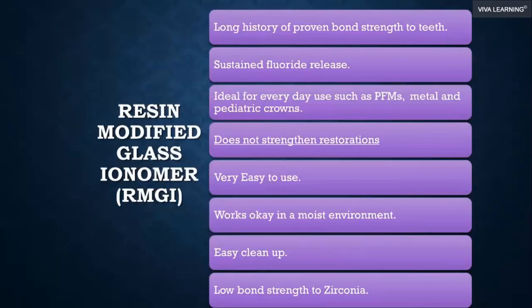Now you have options of cement. If you're going to cement zirconia and you have a long prep, an RMGI will work well. Personally, I don't use a lot of RMGIs, but it has decent bond strength. You get fluoride release out of it. You can use it for PFMs as well as zirconia. It's easy to use and the cleanup is easy, but the bond strength to zirconia is only going to be okay.